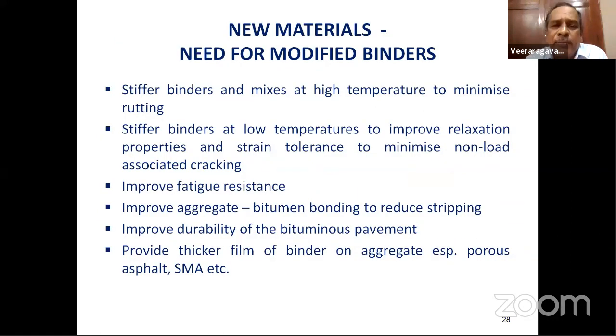At the same time, when materials are not available, I think there's a need to consider alternate materials. Among the alternate materials that we have started using, stiff binders and mixes at high temperature are required to minimize rutting. But stiff binders at low temperatures are likely to crack, non-load associated cracks. But we find that when you use some modified binders, they improve the fatigue resistance. They try to improve the aggregate bitumen bonding. There's an improvement in the durability, and they provide a thicker film of binder on the aggregates. As a result, they last longer.